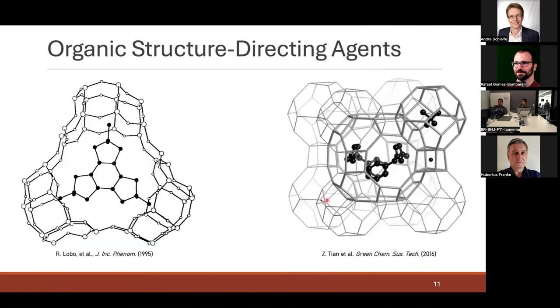So in this case, we were among the first to think about fitting molecules inside zeolites with calculations, right? This sort of 30-year-old concept. Like I said, if the crystal grows around the molecule, ideally, one should be able to calculate how well a molecule fits a crystal and try to steer the crystal in formation in a certain direction based on the shape matching between the desired geometry and the molecule that one would put in there. And this kind of worked, but kind of didn't, because folks would typically design that molecule for this pore, and then they go make it, and a different pore gets formed that also fits this molecule, right?